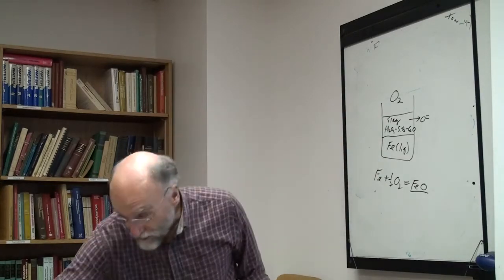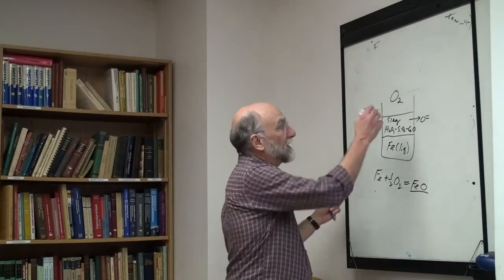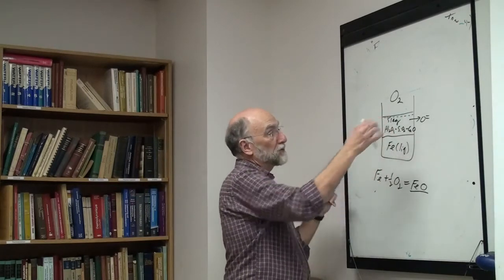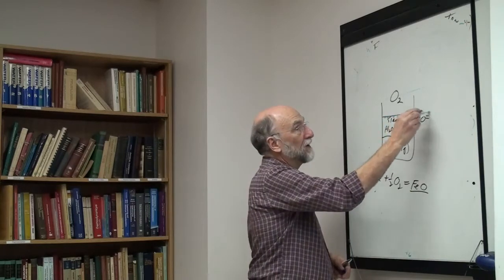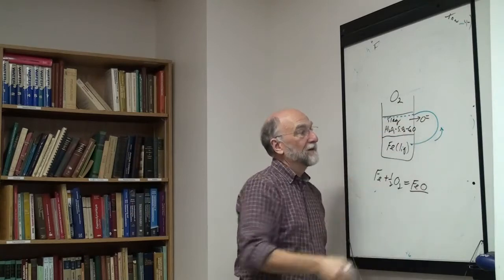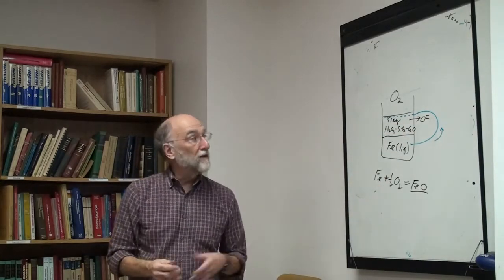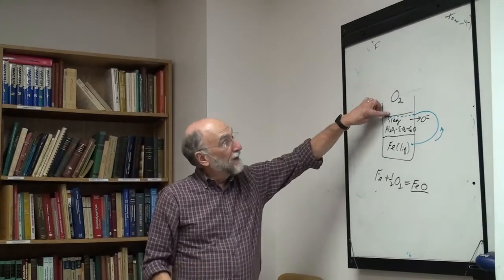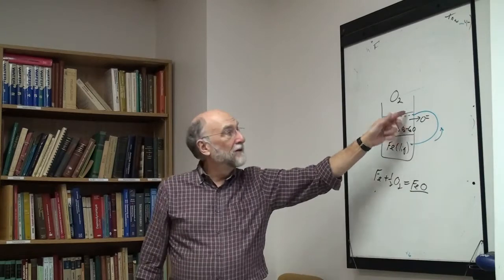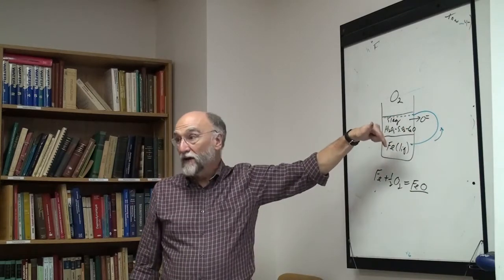But now if you were to make an external electrical contact, so let's say you put a metal grid, a platinum screen, on the surface, for example, and you connect that up through an external circuit where electrons can move. Now you suddenly find the reaction becomes very rapid. An oxygen atom lands on the surface, picks up 2 electrons, becomes an ion, and diffuses through very fast.